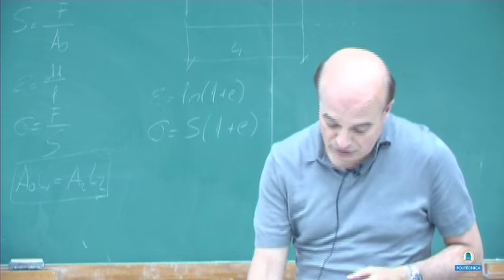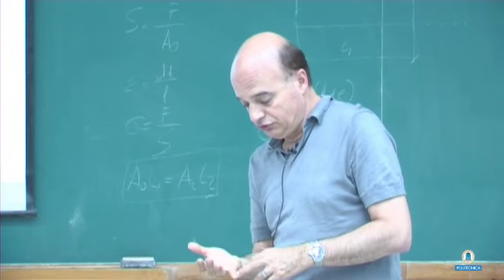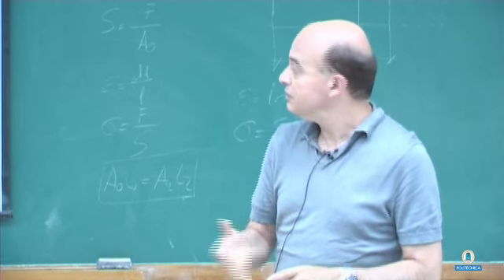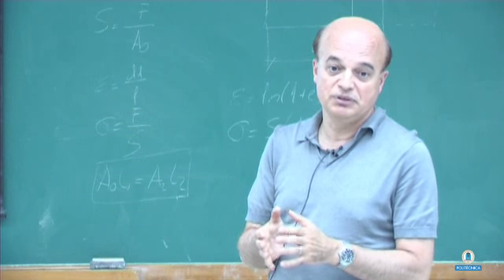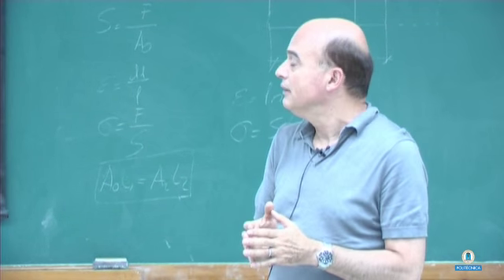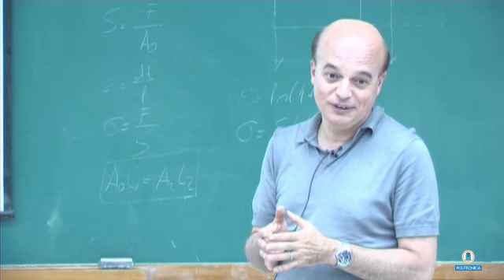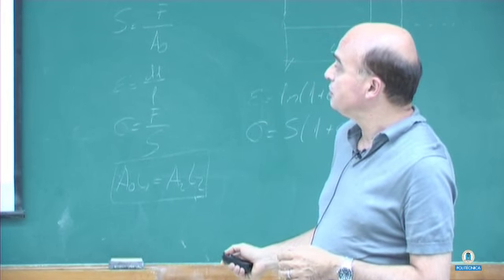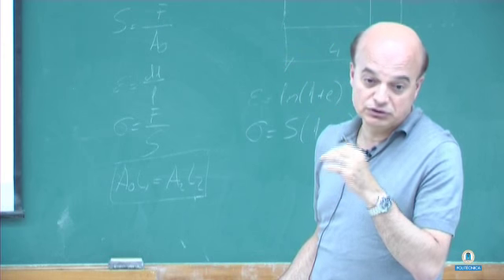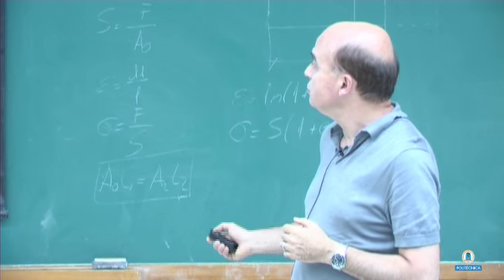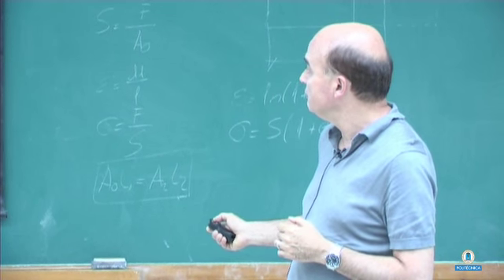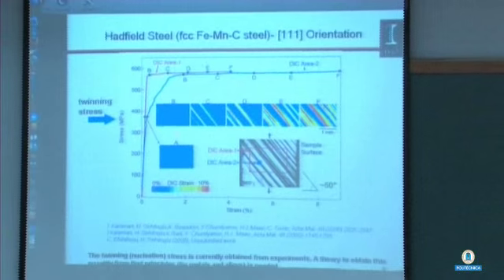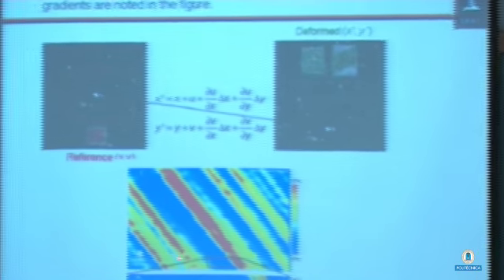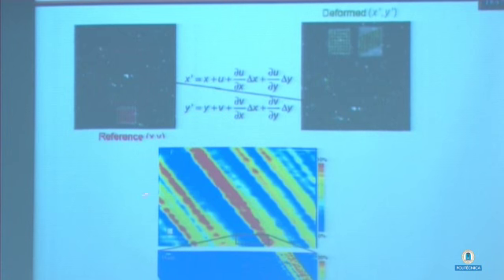One of the things we have been working on, we're working on two things. The first thing, this calculation of the twinning stress, we've been working on for the last 4 or 5 years, okay? And the second thing, we've been working on digital image correlation for the last 4 or 5 years as well. And we're trying to push digital image correlation to very small regions or high magnifications. So if you look here, the strain here at this scale in that twin is of the order of 10%, okay? But we know that in this alloy, the twinning strain is of the order of 35% or so.